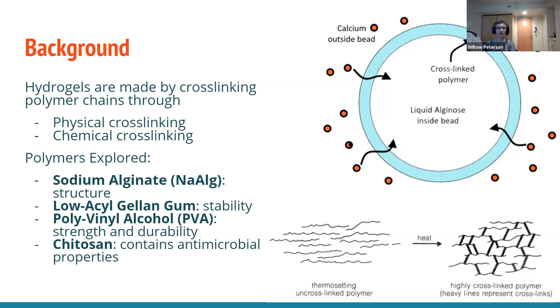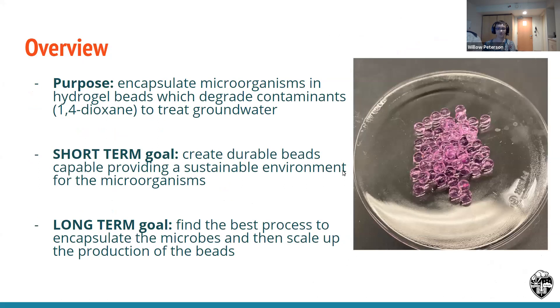The polymers we have been exploring are sodium alginate for its nice round structure, low acyl gellan gum for its stability and ability to form firm beads, PVA for its strength and long degradation time, and chitosan for its antimicrobial properties to prevent the gels from molding. The purpose of our work is to encapsulate the Rhodococcus into the hydrogel beads to degrade contaminants such as 1,4-dioxane, which is a carcinogen, in order to treat groundwater. In the short term we've been looking to create beads that are durable and able to provide an environment for the Rhodococcus, and longer term we are looking for the best method for encapsulating these microorganisms and then scaling up our entire production process.